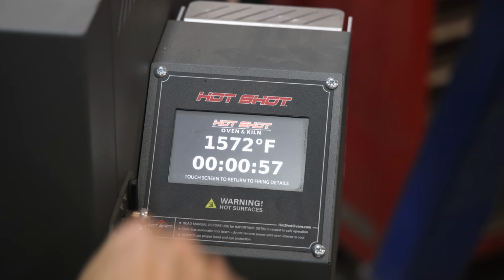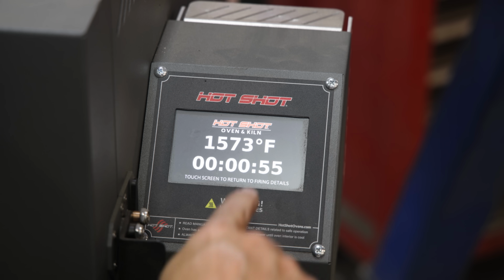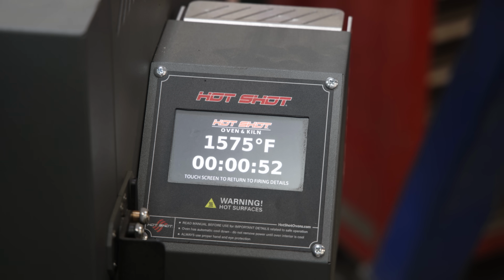Okay, so it's hit 1575. I've got a hold time in there for 1 minute, just to kind of stabilize it, so we should be stabilized at 1575 now. And then after that 1 minute goes by, it should start a countdown for 1 hour and 30 minutes. It's going to keep the temperature within 5 degrees, give or take, of that temperature.